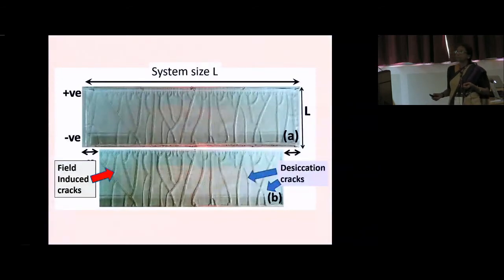Now, this is a pattern after complete drying. And here what happens is that some more cracks appear from the negative end, and these are due to desiccation. They are not the effect of the electric field. They can be identified because they are coming from the negative end, and because we want to study the effect of the electric field, we have separated these cracks. That is, the field-induced cracks are these ones which form the trees, and the desiccation cracks are these which sort of prop up the trees.